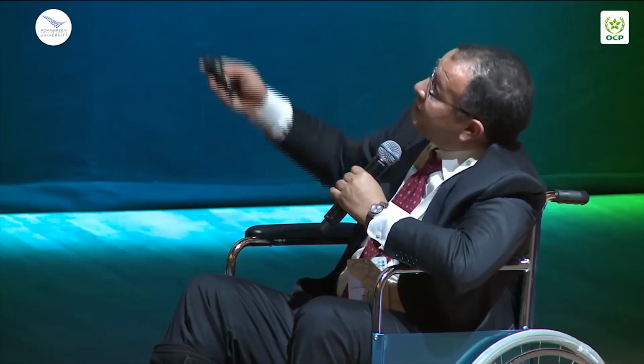And this material is not commercially available, so I'm hoping we can do it with the OCP folks and the R&D folks here. It will be very interesting. And you can see now we move from 100 milliamp hour per square centimeter to almost 250. So now we can talk about some real density, you know, that are very similar to the spinel, for instance. So the volumetric density basically more than doubled in this case.